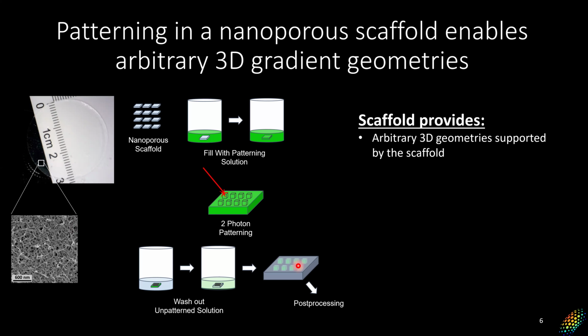And it's the scaffold that gives us arbitrary 3D geometries, right? Because we're not trying to build up off of a 2D surface. We're actually filling in pores in a 3D structure. So it's everywhere supported by the scaffold, and you can make arbitrary 3D geometries. And this is what gives us our gradient index properties. Because, for example, if this is a polymer resin, just by controlling the laser power, you can control the degree of polymerization, and you can control the degree to which these pores are filled.